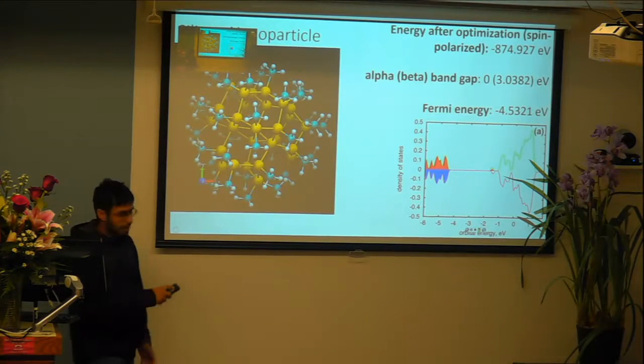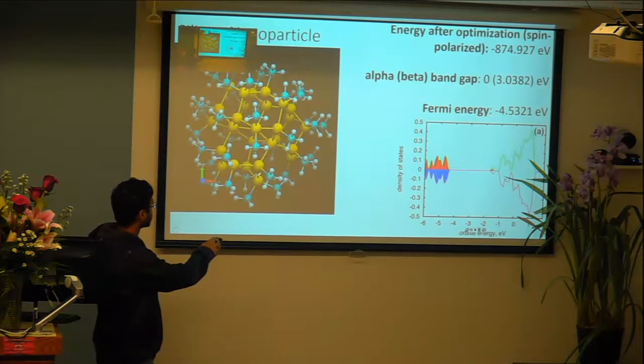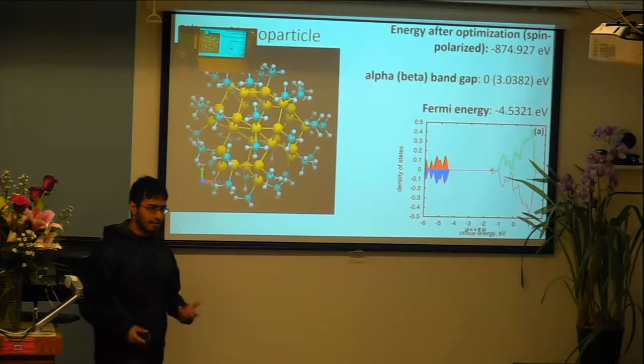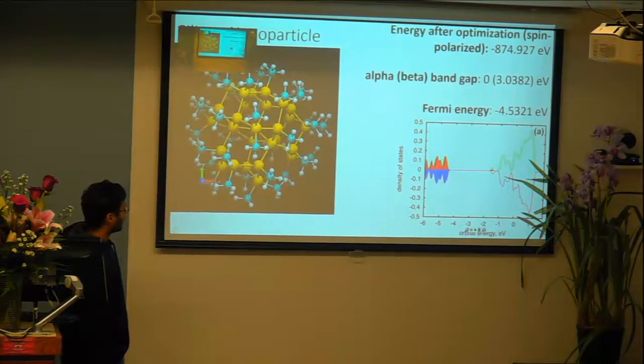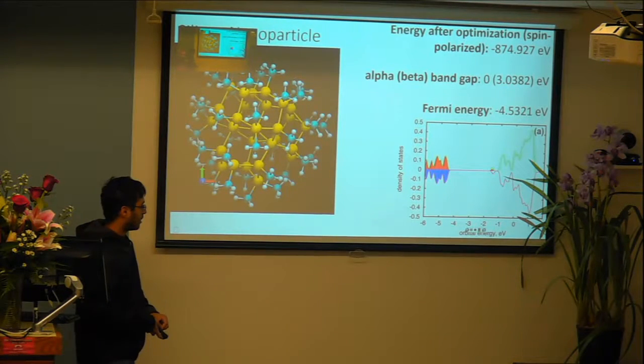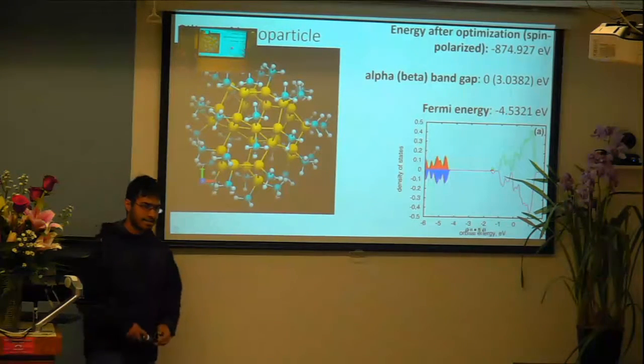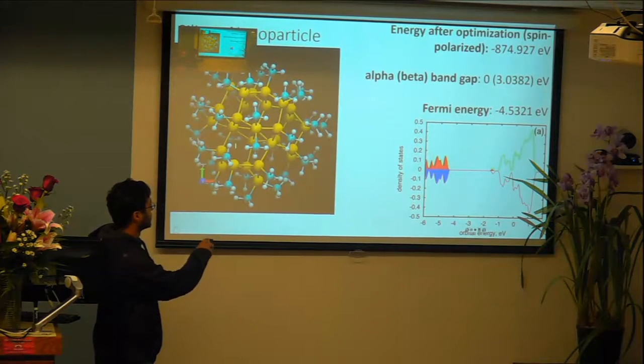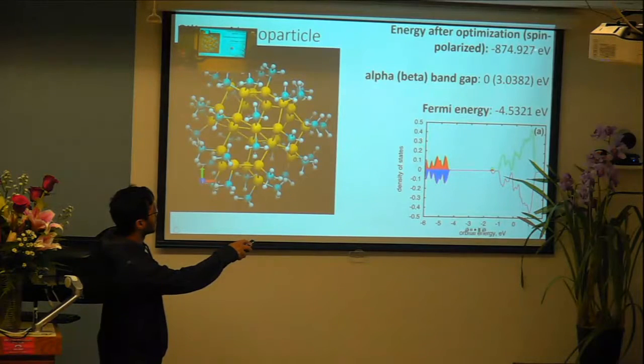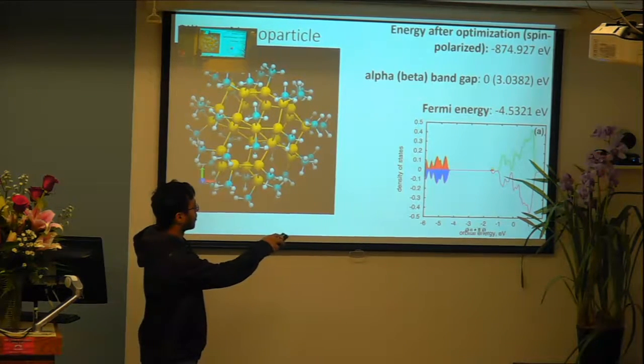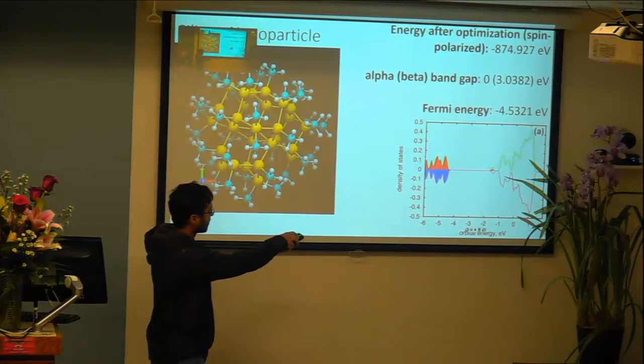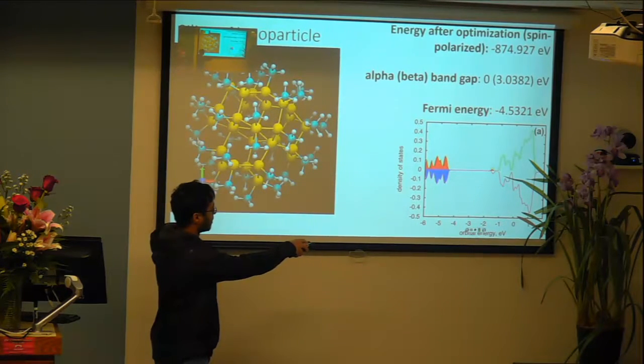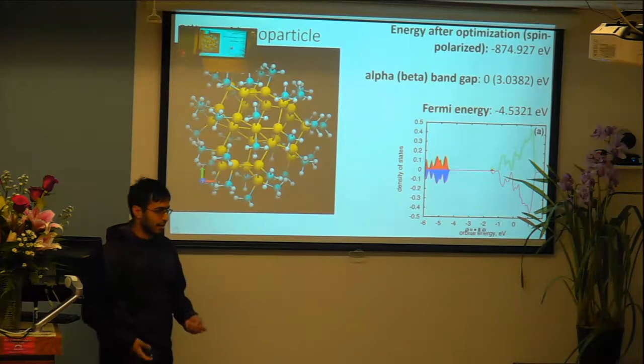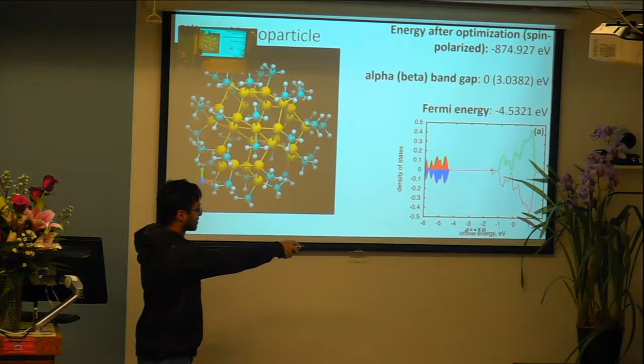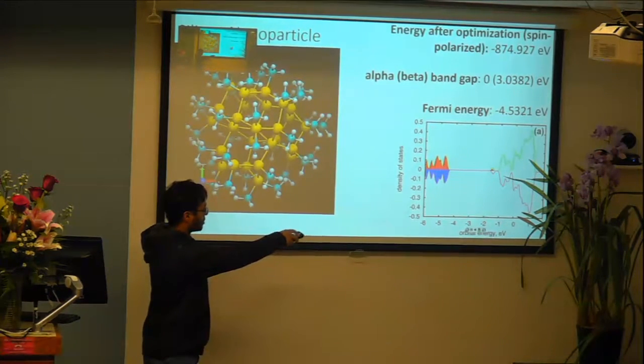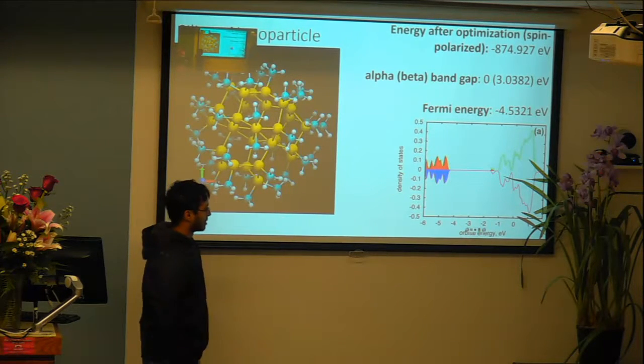So on this slide, there's a quick movie. It's going to be very difficult to see, but this is optimization of the silicon nanoparticle by itself. So this was run using, I think, 1,000 ionic steps in VASP in order to optimize the silicon nanoparticle. And you can see the total energy after optimization, as well as both the alpha and beta orbital band gap. So the alpha represents the band gap for the red states in the density of states, whereas beta represents the filled blue states and all of the states below 0 on the vertical axis. And then finally the Fermi energy as well.